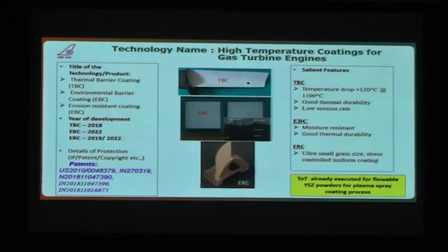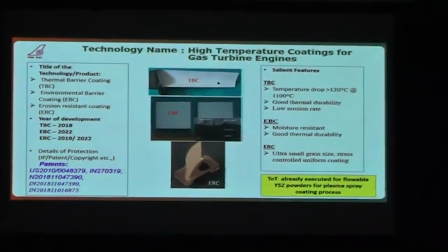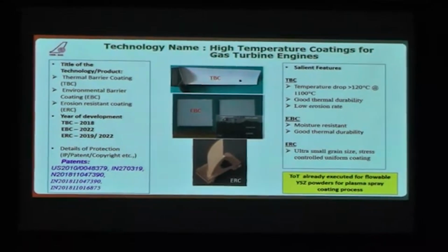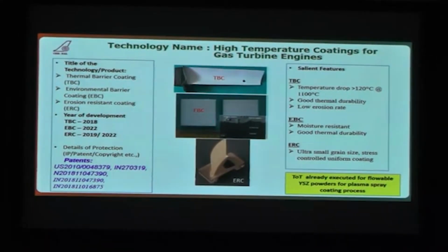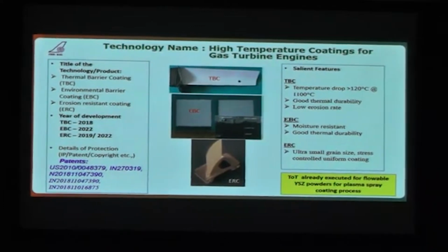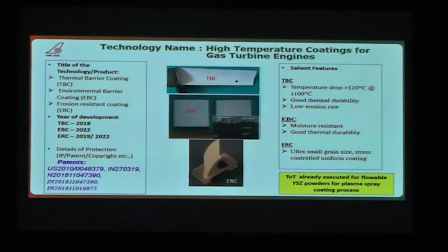The salient features are that these TBCs are compatible with high working temperatures of 1100 to 1200 degrees, and you can achieve up to 120 degrees centigrade temperature drop so as to protect the bare metal from the very hot zone. They have very good thermal durability and low erosion rate. Our EBC, the environmental barrier coating meant for composite components, is moisture resistant and also has very good thermal durability. The other coating is the erosion resistant coating for our compressor blades. These are all made by sputter coating techniques, which give ultra small grain size, stress controlled uniform coatings, with a balanced ductile and brittle nature.